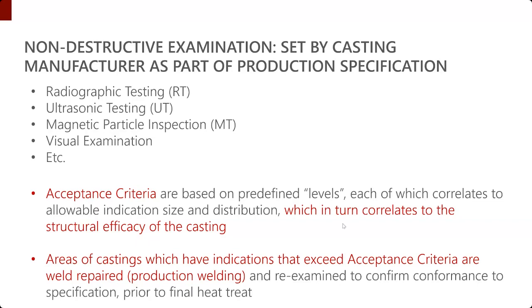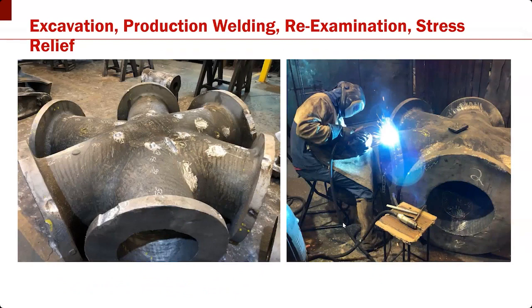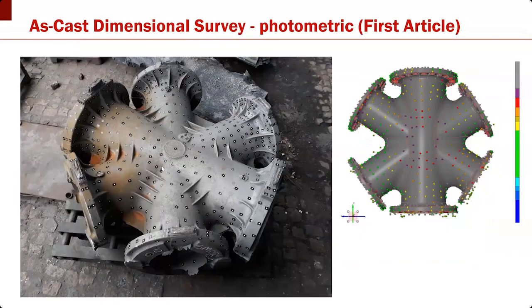Something interesting about steel castings is that always in the production of a casting, when it is cast, the non-destructive examination will be performed, and they will always find pieces of it that don't meet the acceptance criteria. That is expected. It's part of the whole process. So they have something variously called weld repair or production welding because it's part of the production. That piece, the little rotten piece, is arc gouge weld repaired. So it's removed, it's filled with the weld. The testing is reperformed. So we go through this process until everything meets the acceptance criteria. And then finally, because it's been welded, there's a heat treatment for residual stresses.